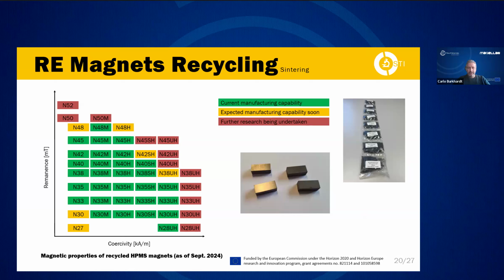What has been done in a project and now also in a framework of commercialization, we can say more than 3,000 different magnets have been produced in the last couple of months, and we're in the middle of upscaling the processes. And you see everything that you see in green here. These qualities have been made from 100% recycled material. Important, not with added virgin material. With adding virgin material, you probably can push the boundaries even more, depending on how much recycled material you can put in.